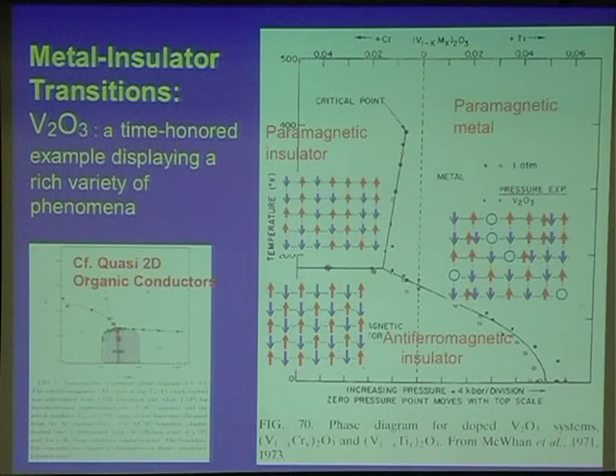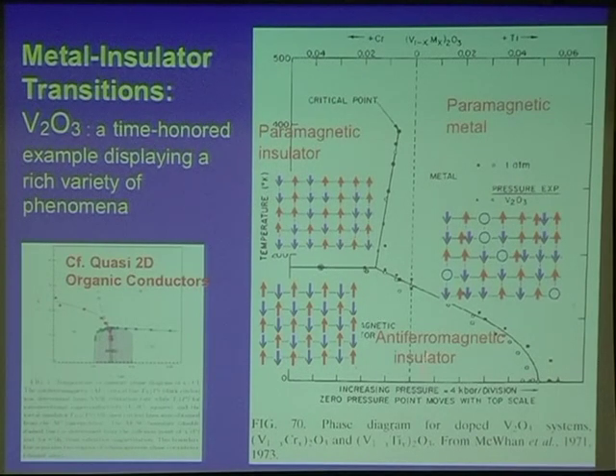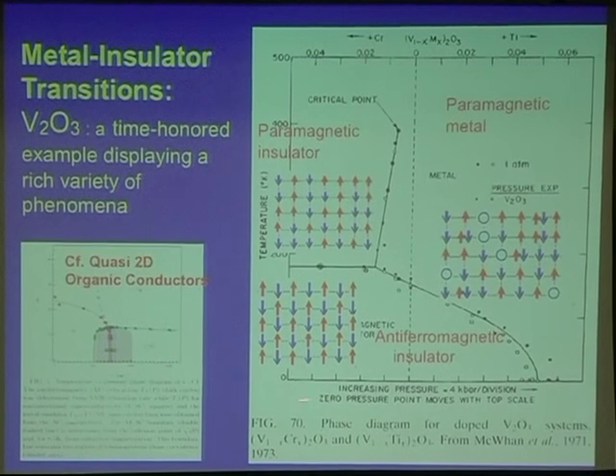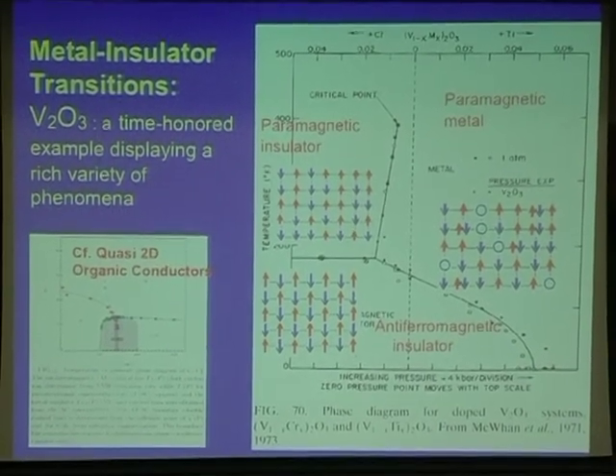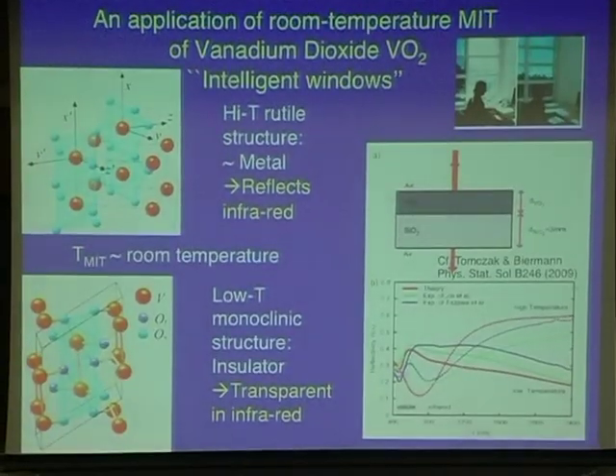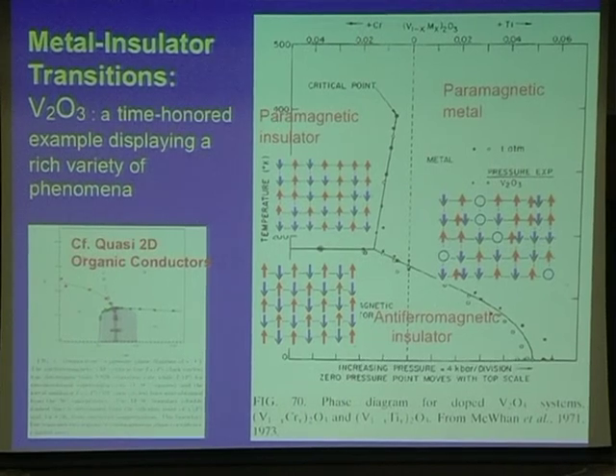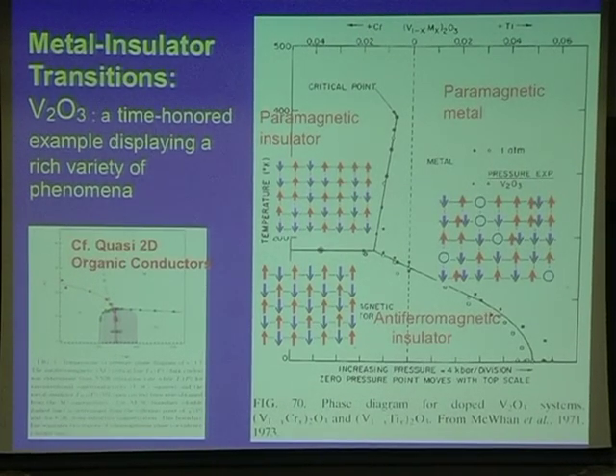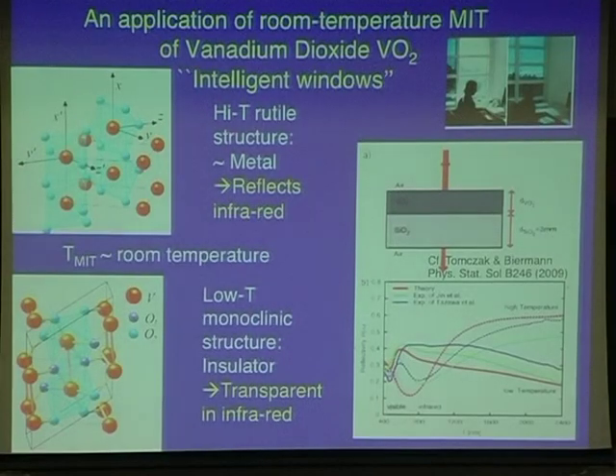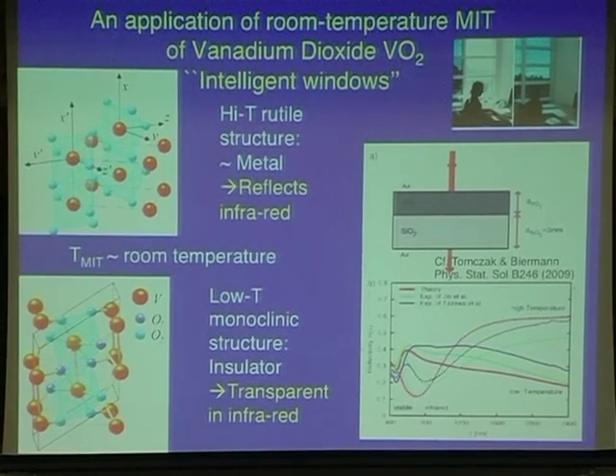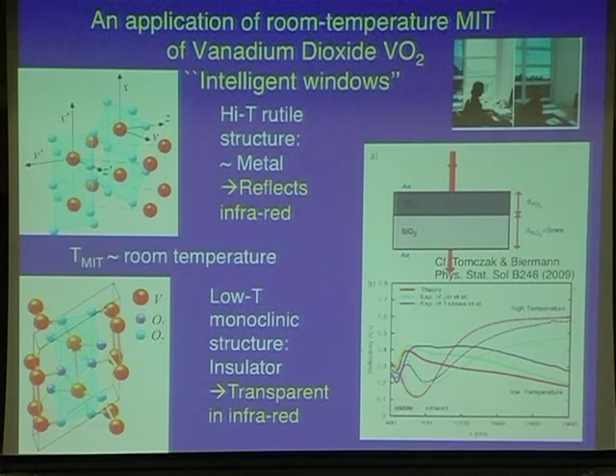This is a system, a vanadium oxide, that has a series of metal insulator transitions. And when you actually cool down, this paramagnetic insulator actually orders into an antiferromagnetic insulator, so you have magnetism. So you see that by tuning a simple parameter like pressure, you can actually switch between these different phases. This sort of phenomena is not only interesting from a fundamental point of view, but is also potentially interesting for applications. And this is an example of another vanadium oxide, vanadium dioxide, which has the good taste of having a metal insulator transition at a temperature which is very close to room temperature.